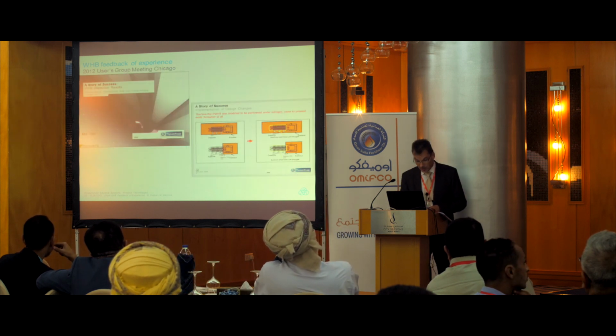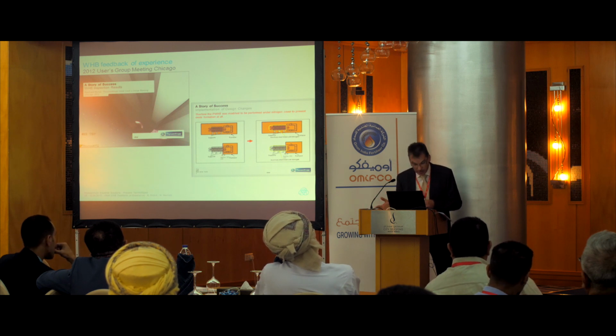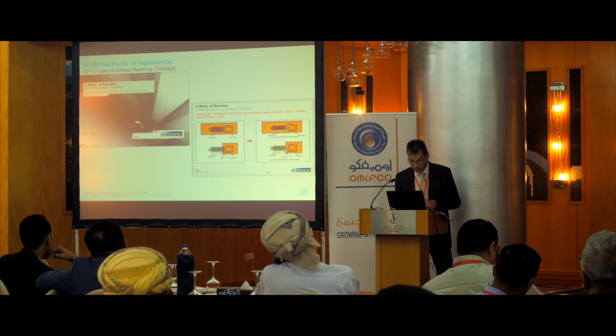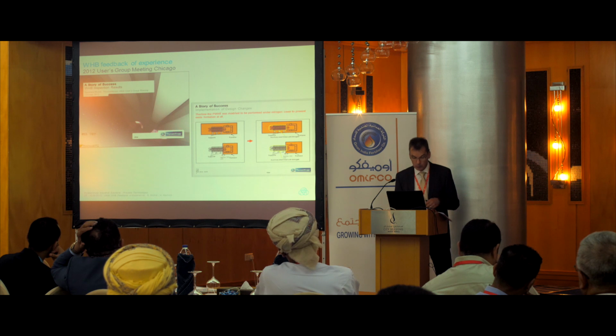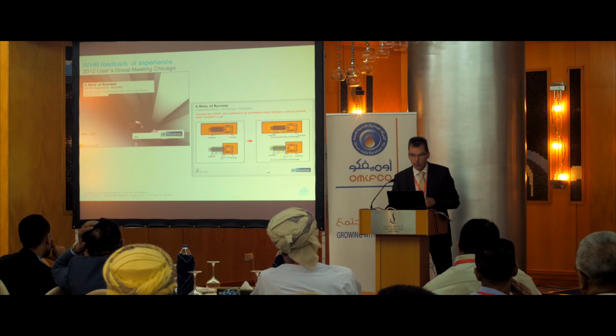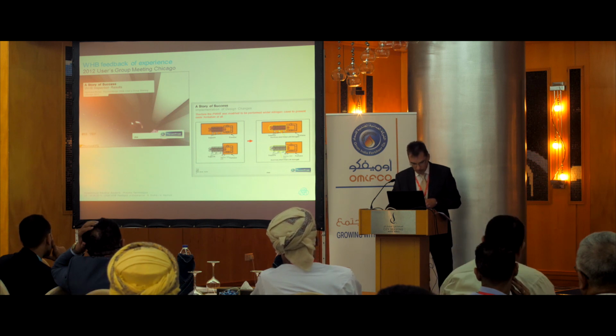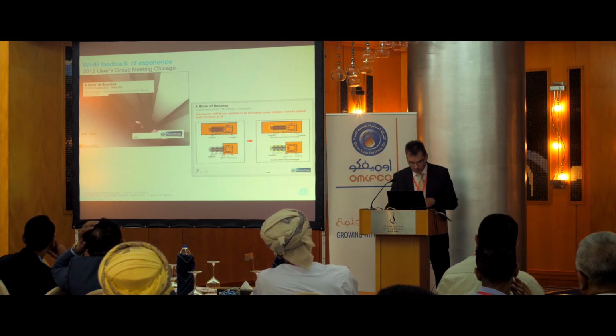So, was this the story? Several borescope inspections of boilers in operation during 2008 and 2012 at different plants proved that the condition of the boiler on the shell side was clean, free of spalled-off oxide layers and without deposition of magnetite on the tube surface. You see on the left side a typical picture with the borescope and the tube very clean and the wall clean. Consequently, our paper at the ammonia users meeting was titled A Story of Success.